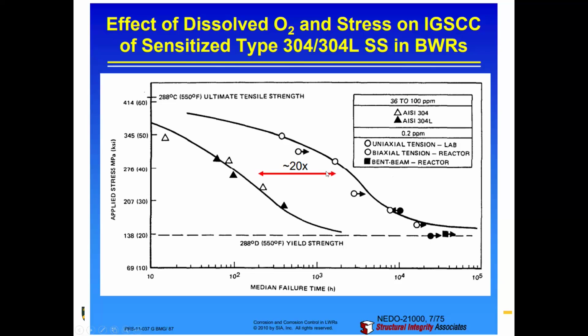So total oxygen concentration, you can see if you have about 100 ppm, which is pretty high. That's way higher than you would have for normal water chemistry. But I think the authors were just trying to make a point with this slide. This is way too high to operate a BWR in general. But if you compare that to 0.2 ppm, you can see how much more stress you need to apply to reach failure time-wise. It bumps things up by orders of magnitude by changing oxygen concentrations. This is just to make a point.